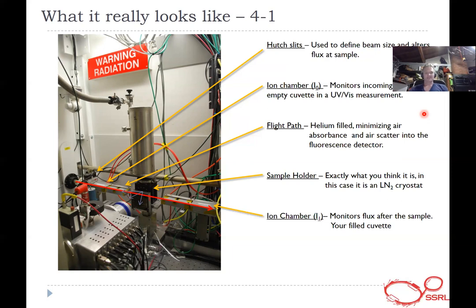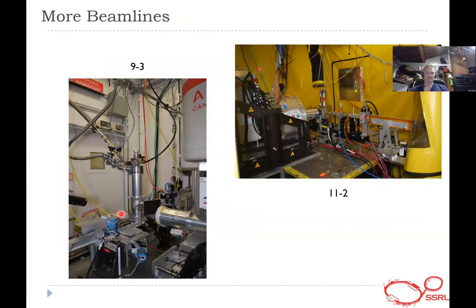Then an ion chamber after a second flight path, you can see a second flight path on the other end of the sample. And in this case, you see I1, which you would use for your cuvette, I guess, after the sample. So characterizing the beam after it's gone through your sample. And this is important if you're doing a transmission experiment. And then in this case, you can see a fluorescence detector. Here it's a germanium 30 element discrete element germanium detector. We have different geometries on beamlines.